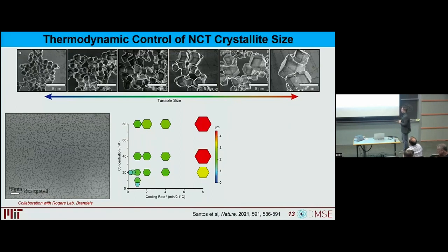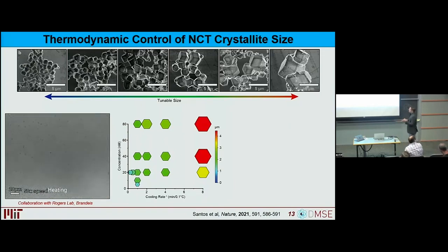So this is about 50x speed. What we can see is that as we heat it, very quickly they will all melt away. And at a certain point, we're going to start cooling it down. And within about 2 minutes or so, we can start to see the crystallites actually start to reform. And these are not just amorphous blobs, these are actually Wulff polyhedra. If we were able to zoom in on these things, we would see the same types of structures that we're seeing here. So the fact that we can assemble these materials so rapidly, I think, is an interesting opportunity for us to explore a lot of the fundamental dynamics of crystal nucleation and growth and how they're different for these